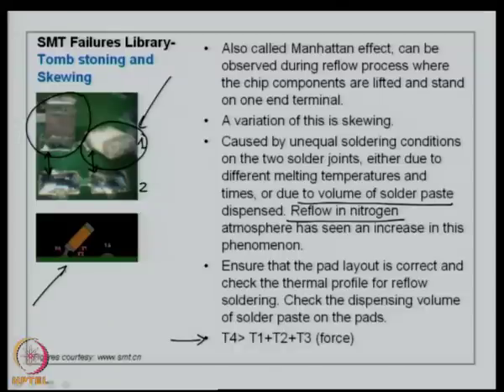Therefore, what has happened basically here is this solder paste has got activated much faster. The melting temperatures have been attained in a much lesser time compared to this pad and the solder paste, and therefore, this solder paste here by surface tension has pulled the component towards its side, and it is not at all attached to this pad.